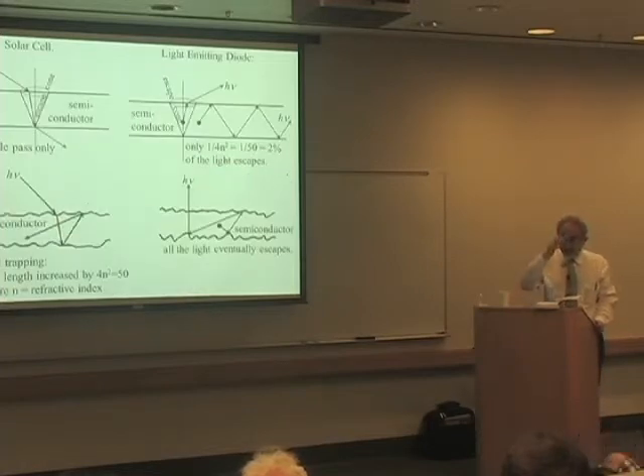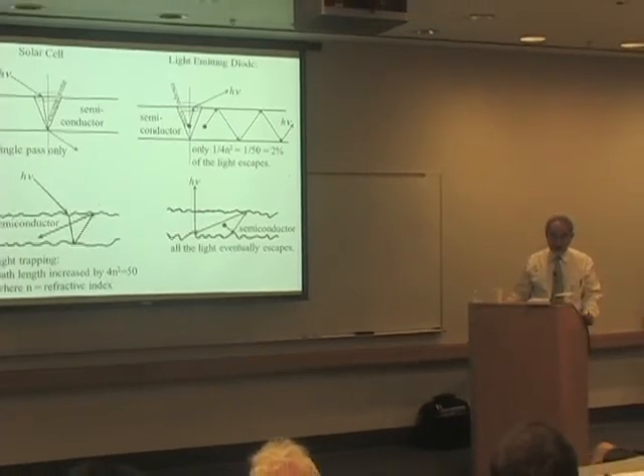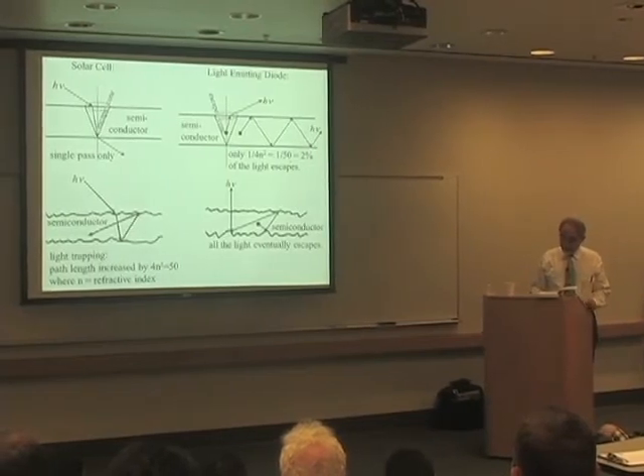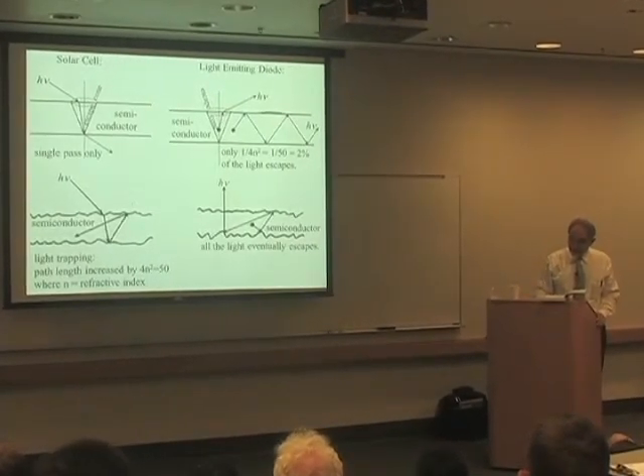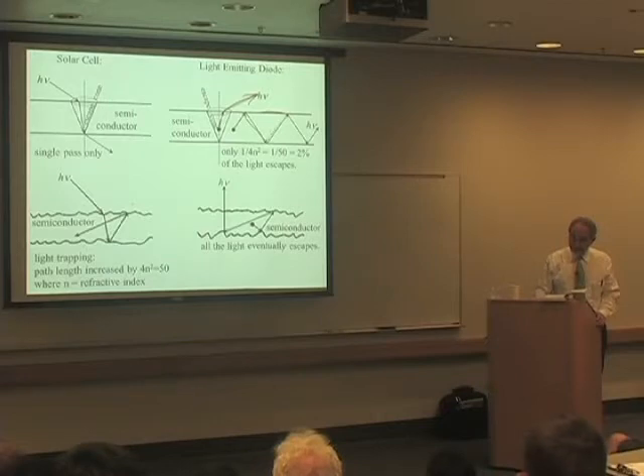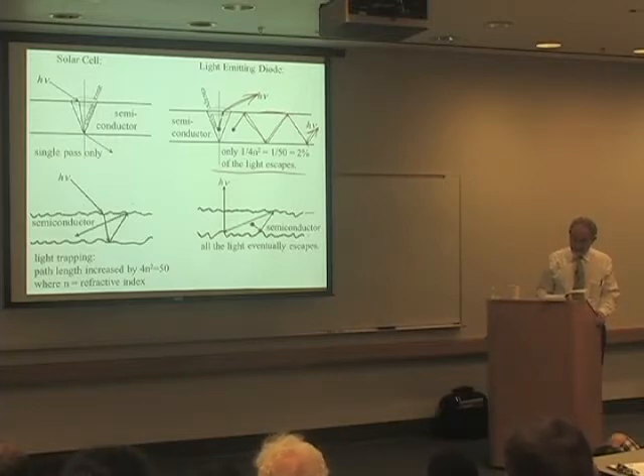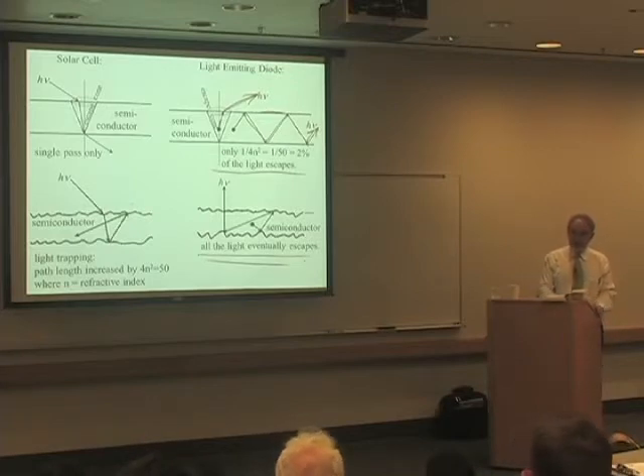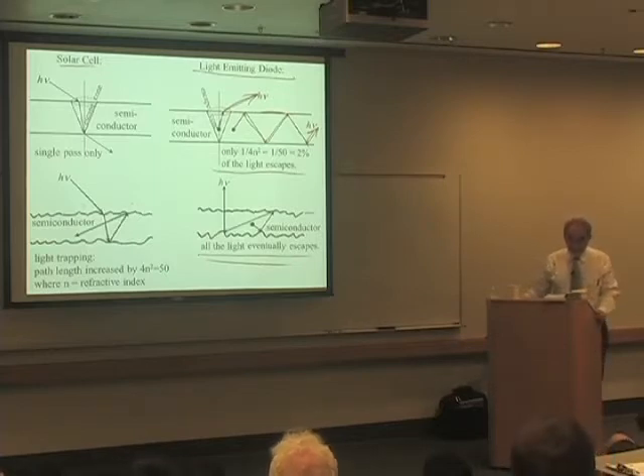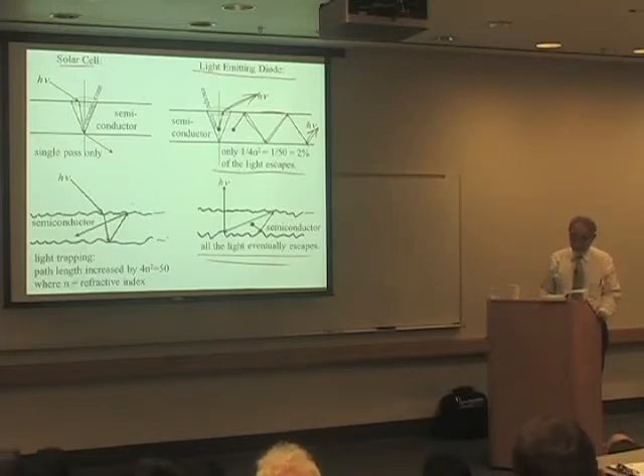And in fact, the same issue arises in light-emitting diodes, which I think people here are very familiar with. And that is, if you have a plane parallel light-emitting diode, only a small percentage escapes, perhaps as little as 2%. And then the rest of it is trapped and bounces around and eventually gets wasted in some absorber. And so this is a very naive LED. However, if you make the surface of even one surface of the LED rough, eventually all the light escapes. And so it's sort of an indication. The solar cell and the light-emitting diode are brothers. They're really the same device. One is run backwards and one is run forwards. But they both benefit from breaking the plane parallel symmetry of a thin slab.